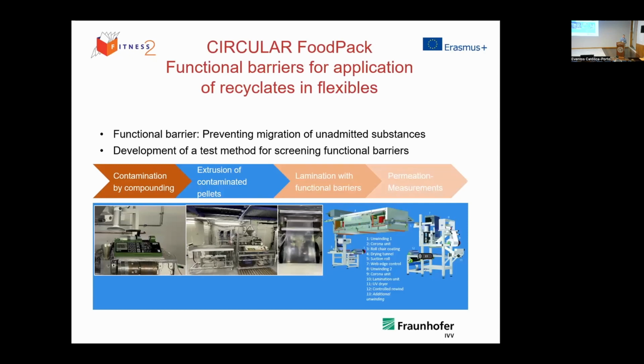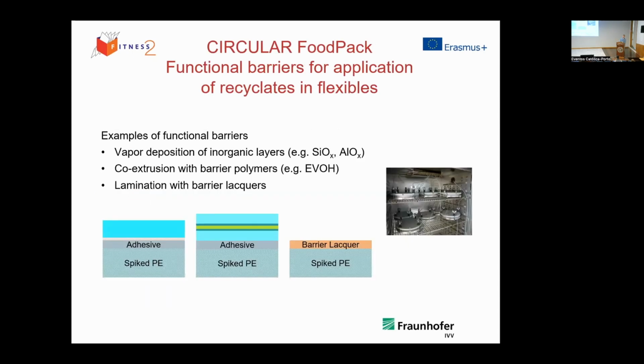substances into the food, and to have an idea which packaging or which barriers work the best, we have developed a test method where we first contaminate a polymer by compounding, then extrude the contaminated pellets into films, and then we can laminate the films with functional barriers and do some permeation measurements. So how good the barrier performances of each barrier film are. And just a few examples, there are inorganic barrier layers, there are co-extrusions, and there are also barrier lacquers which can be applied.